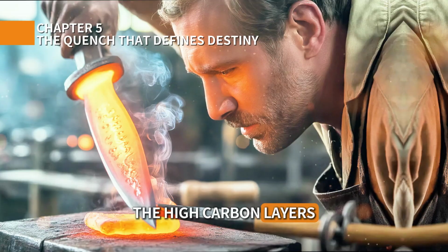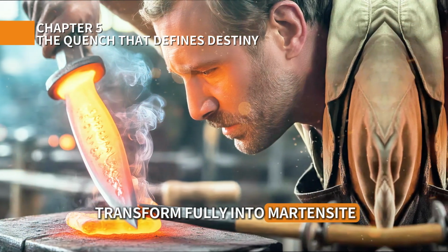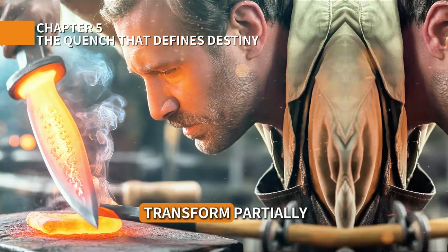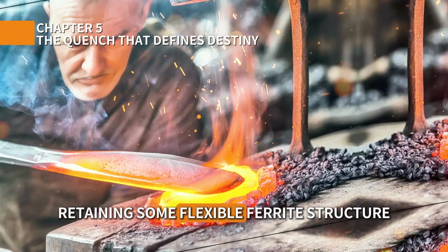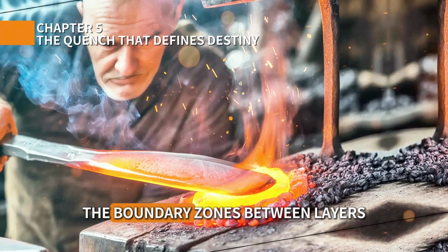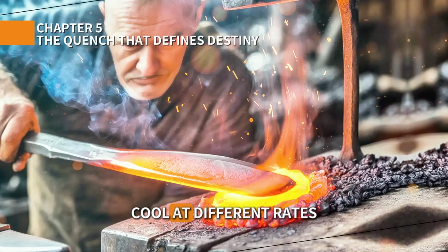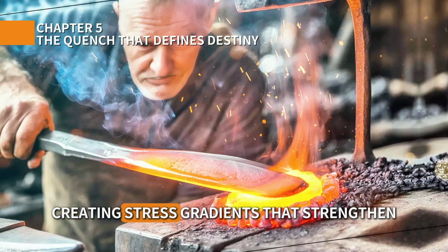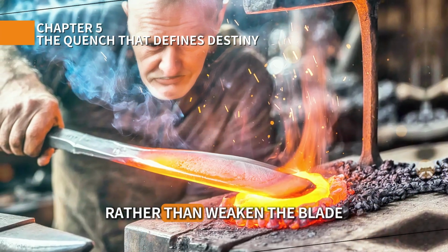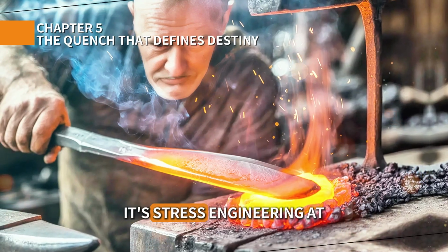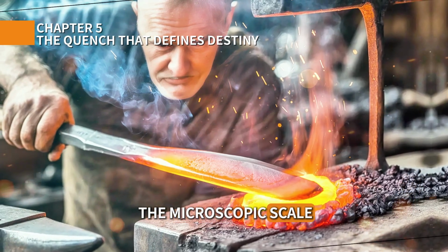The high-carbon layers transform fully into martensite. The low-carbon layers transform partially, retaining some flexible ferrite structure. The boundary zones between layers cool at different rates, creating stress gradients that strengthen rather than weaken the blade. It's stress engineering at the microscopic scale.